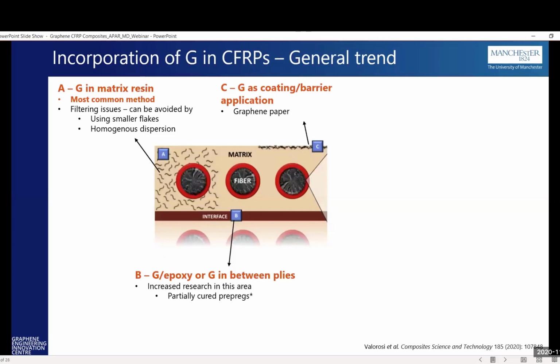The second method is by adding the graphene epoxy as a film in between the plies, for example. Either you could apply graphene as a resin film, or the graphene can be spray coated in between the dry fabric or on the pre-preg themselves. So in the cured laminate, the graphene actually lies in the interface between two different plies. The third one is the graphene can be coated on top of the laminate directly, so it could act as a barrier application.